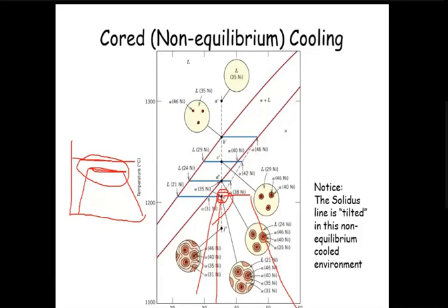If you allow that, then we should obtain only one solid of uniform chemical composition. But due to non-equilibrium cooling, we are continuously freezing every phase of the solid, starting from 46 to 31. We are not allowing it to grow, and due to that, chemical inhomogeneity exists.